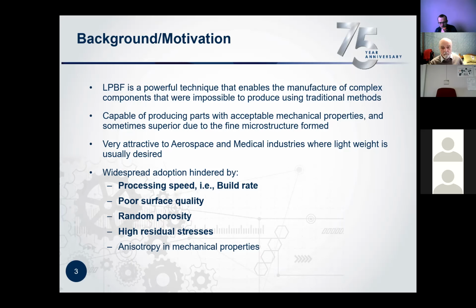Higher residual stresses develop due to the rapid heating and cooling cycles. Of course, when these residual stresses are high enough, they can generate distortion in your part. This can lead to part inaccuracies. It can even lead to cracking or delamination of the parts during the build. And of course, anisotropy in mechanical properties in the as-built condition. We have seen that if you test the material in different directions, you tend to get different properties. But if you apply post-heat treatment on it, you can actually get rid of the anisotropy and recrystallize the microstructure.